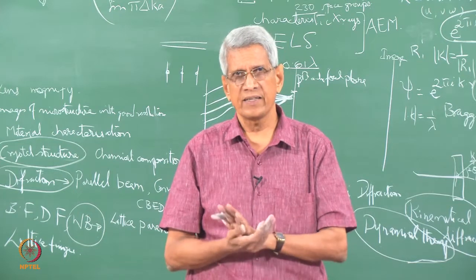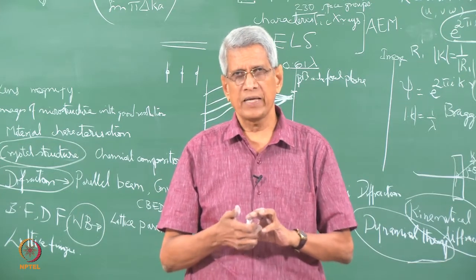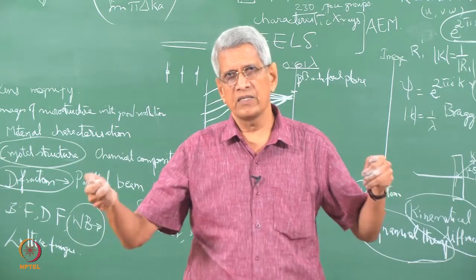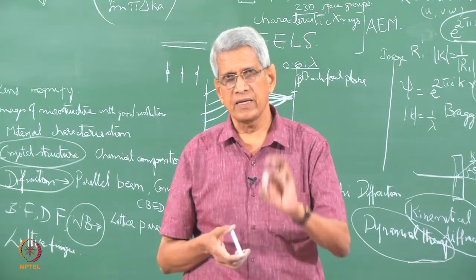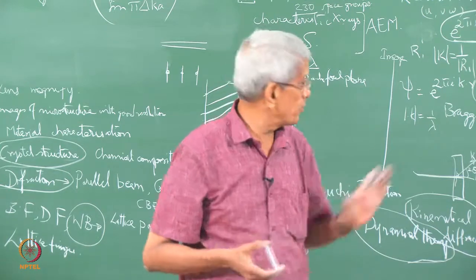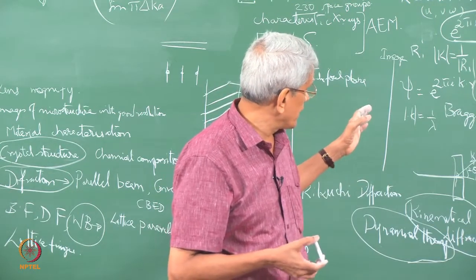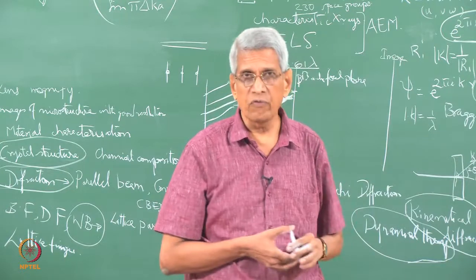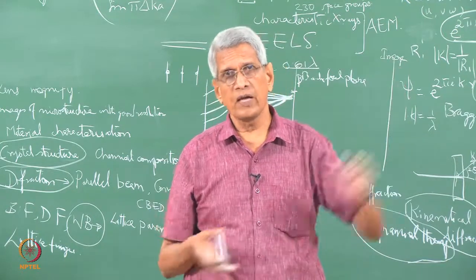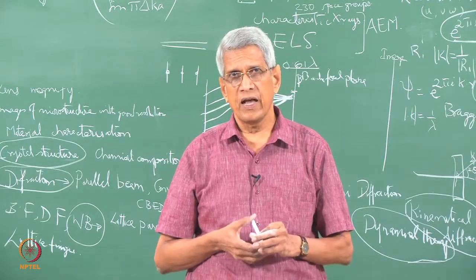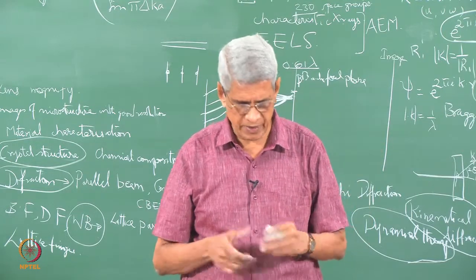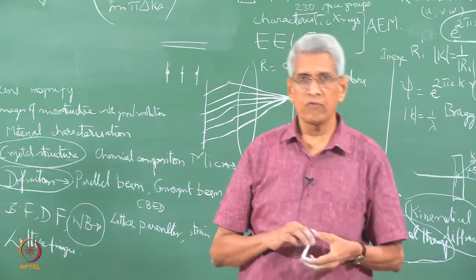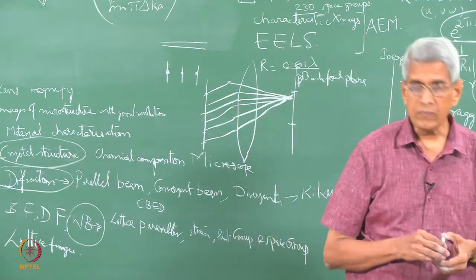In one direction it has a major axis of very large size, and the minor axis is small in width. Because of this, we will be getting streaking in different directions, and looking at the streaking itself, as we have learned, we can find out the morphology of the precipitates. That information we can obtain from the diffraction pattern.